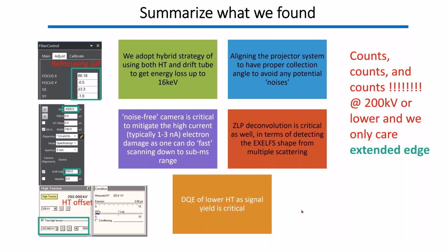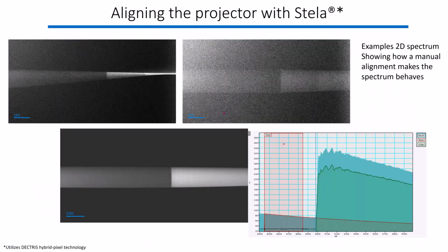So in that sense, we do choose the Stella GIF camera to do this, just because it's good for low high tension. And for this work, we also choose low dispersion, which means 3 eV per channel, because we are a bit more concerned about signal to noise. If you adopt the same strategy, you use exactly the same as what was said before. This is just camera raw, that's why you don't see the proper scale there. And you can see, not exactly the same because they are different cameras, the interference signal on the 2D spectrum, same as we saw before on the K3 camera. And then you can extract the 2D spectrum out from there.